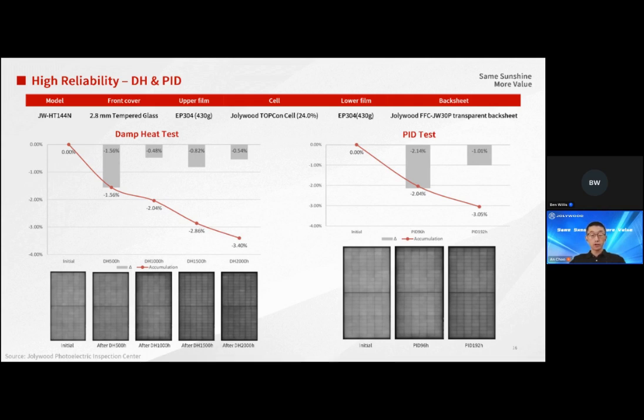After 2,000 hours of damp heat testing, our module showed a power degradation of just 3.4%. Moreover, it demonstrated only 3.05% degradation after 192 hours of PID testing. These results not only highlight the module's superior damp heat resistance, but also its reliability and long-term stability, ensuring optimal performance over its lifespan.